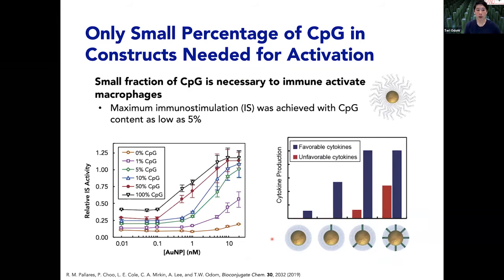And so one of the first interesting findings was that you only need a small amount of CpG to immune activate the macrophages. You actually don't even need a shell of the CpG. So if these green bars just indicate the fraction of the active component for the oligonucleotide, you only need about 5%, which is pretty interesting.